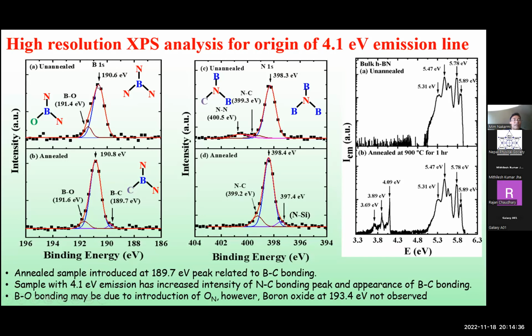In the boron core binding energy, there is a small peak here, boron with oxygen. No, it is actually boron with nitrogen, and this emission is there. This is a mistake, it's nitrogen. In addition to that, we also have one additional peak. It appears in the sample which has 4.1 eV, a small signal from boron binding with carbon, which is not in the unannealed sample, which doesn't have 4.1 eV.